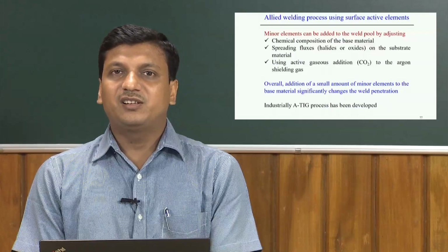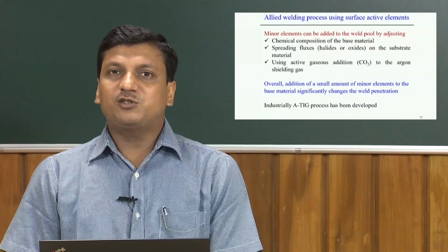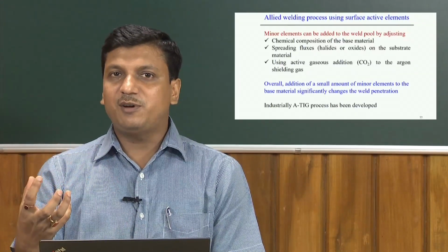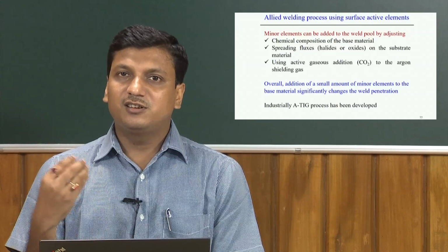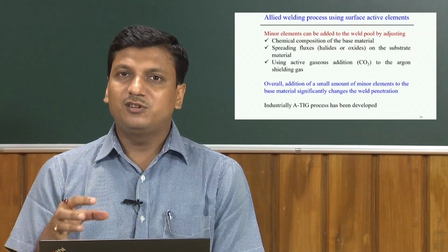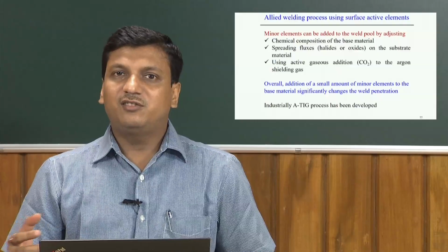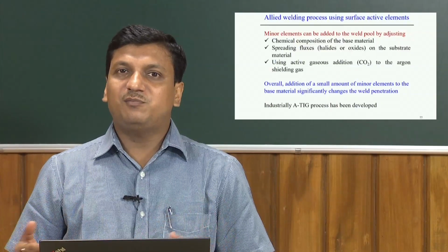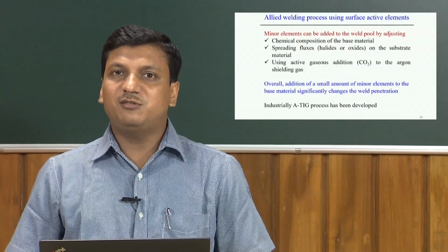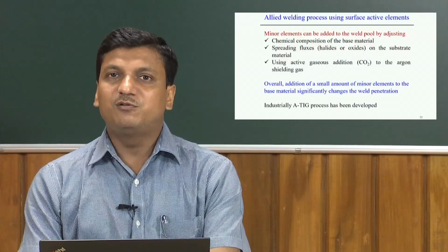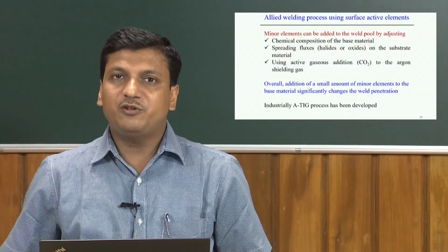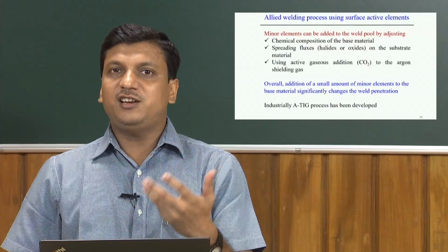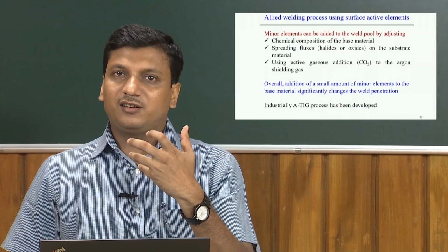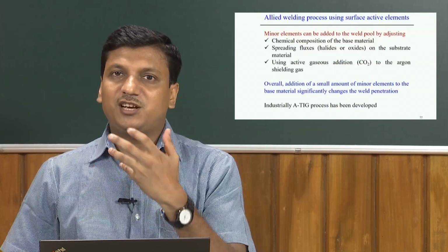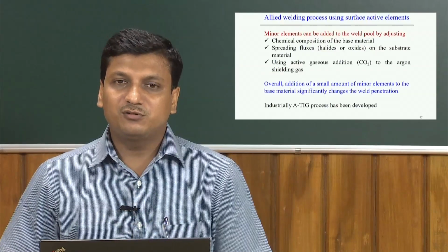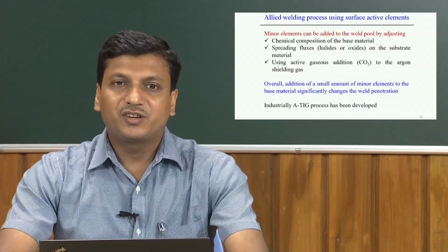That means if it is possible to add some amount of the surface active elements within the weld pool during the welding process, that can bring the positive effect of the surface active elements, that means it can affect the weld pool shape. But what are the different ways to practically bring the surface active elements into the weld pool? So, there are three different ways.